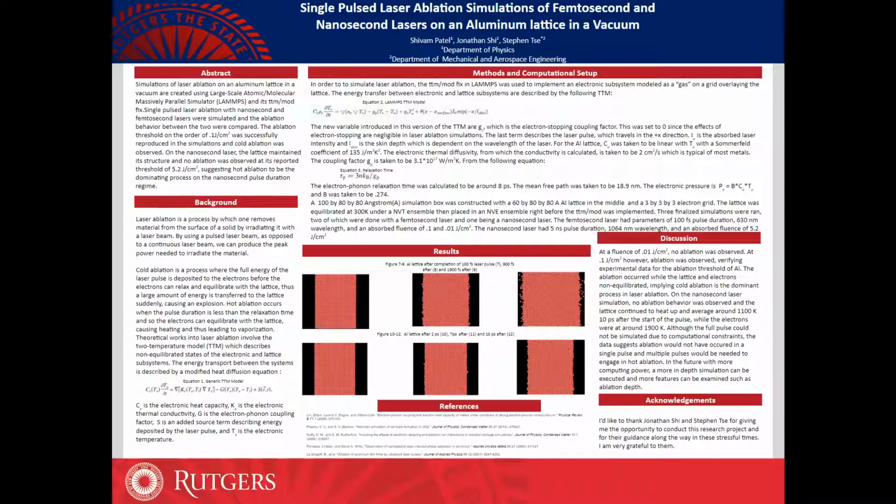simulation at 0.1 joules per centimeter squared fluence. So after the laser pulse was finished, after 100 femtoseconds, we can see that not much has changed in the lattice. After 900 femtoseconds, we can see some excitations, and after 1900 femtoseconds, we can see very obvious ablation behavior.